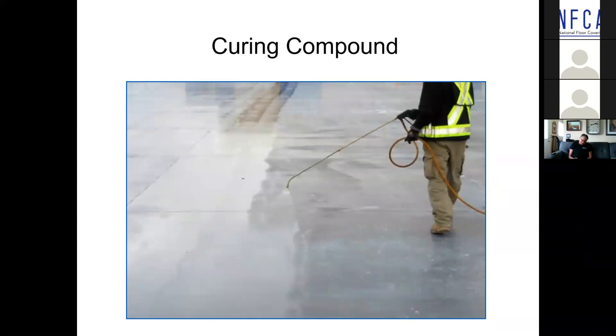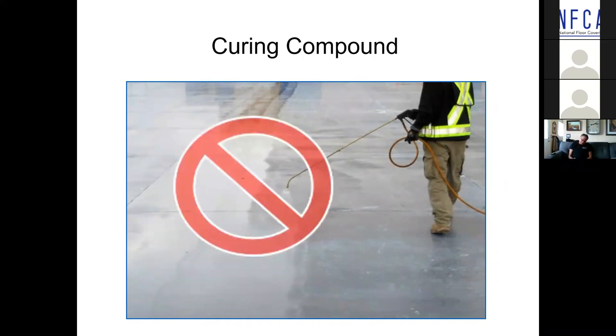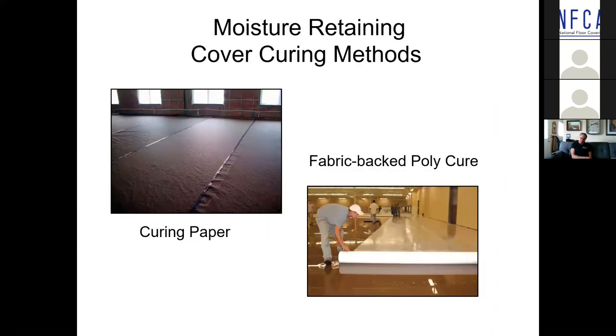And as you're constructing the building and starting to frame out the floors, anywhere where there isn't significant traffic, that residue is still on the surface. So ideally, if you know ahead of time this is a floor that's going to receive a floor covering or coating, in my opinion, it's far better to consider the third class of curing methods, which are basically just moisture retaining covers. I've used dry wet strength curing paper for years. Also used in the more arid regions of the country or in the hotter, windy conditions.